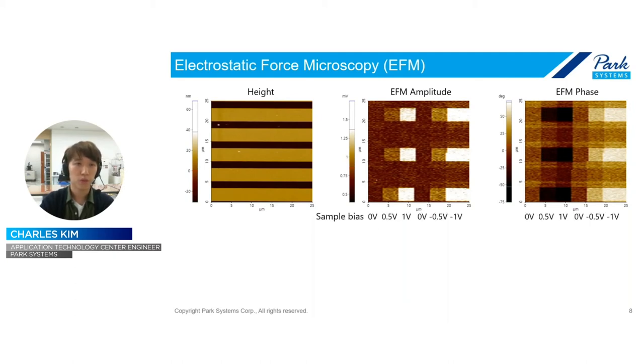So to measure this image, I changed the sample bias from 0, 0.5, 1, 0, minus 0.5, minus 1. Plus 0.5 and minus 0.5 have different force directions, but the color of their electrostatic force in the EFM amplitude is the same. But in the EFM phase, minus has the darker color, which means the negative phase, but plus has the positive phase. So from these two images, you can analyze your own sample surface electrostatic property.